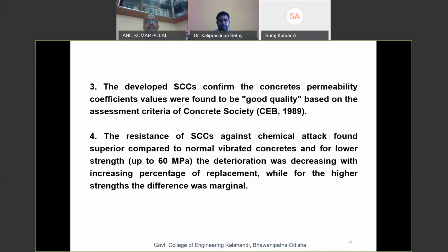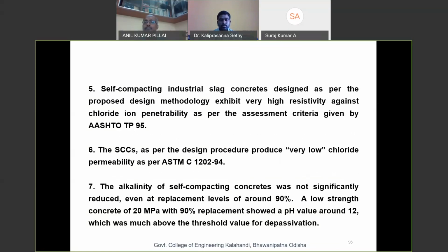And for lower strength, that is up to 60 MPa, the deterioration was decreasing with increasing percentage of replacement, while for the higher strength concretes, the difference was marginal. And self-compacting concrete that is designed with the proper mix design methodology exhibits very high resistivity as per the AASHTO TP 95 criteria, and it also showed a very low chloride permeability as per the standard ASTM C1202-94.